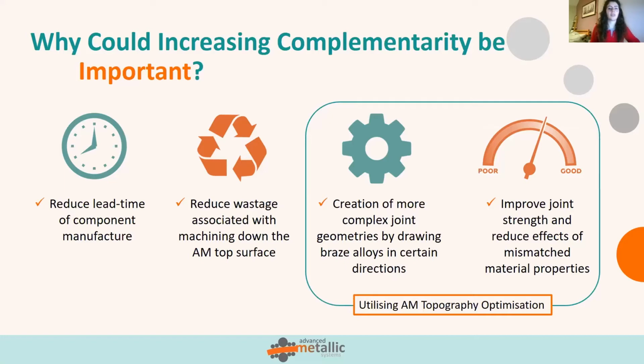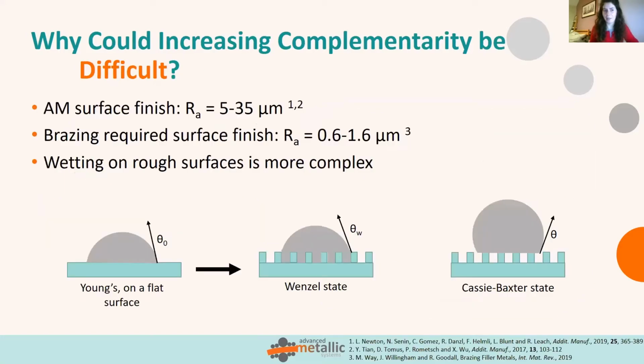So this sounds really cool - so why isn't it happening yet? The typical surface finish of an AM part, according to its arithmetic average roughness, the RA value, is between 5 and 35 micrometers, whereas the required surface finish for brazing is between 0.6 and 1.6. So there's quite a vast difference between these two values.